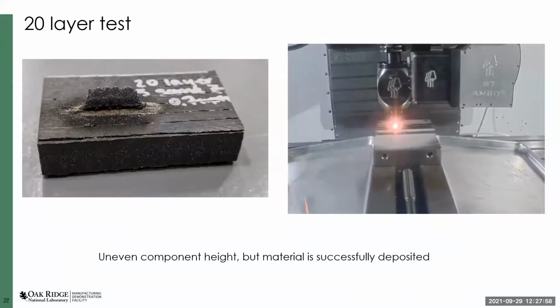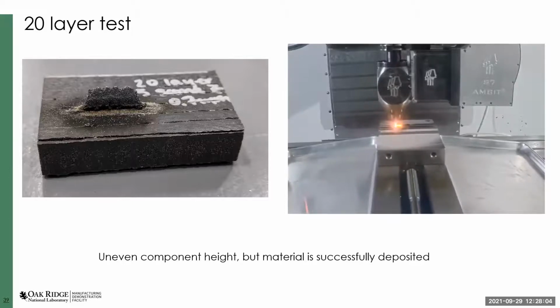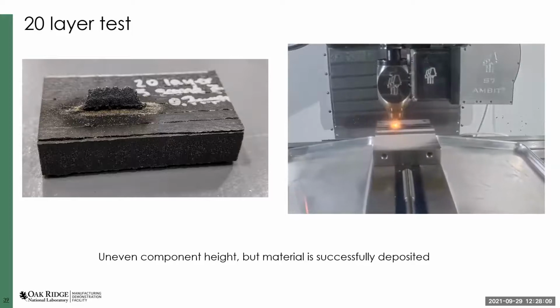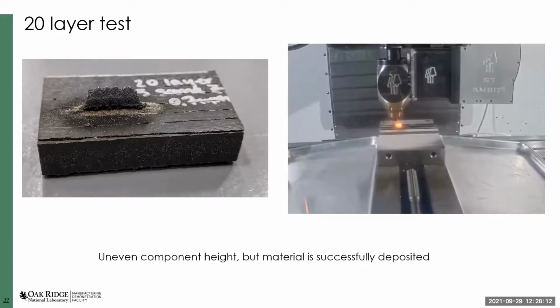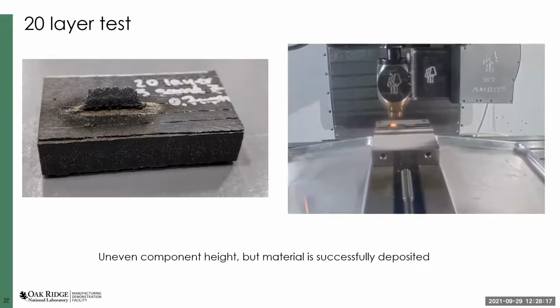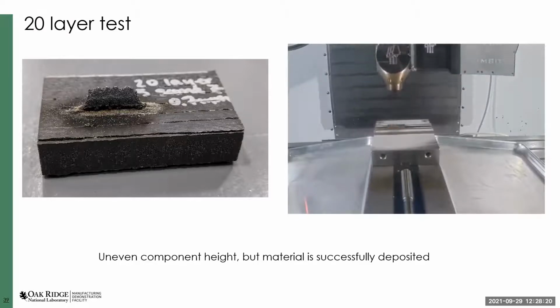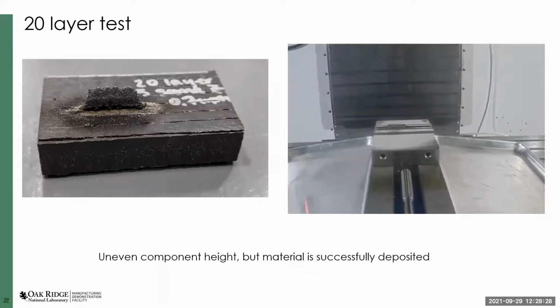You can see that initially there's still that pretty intense flaring, but that decreases over time as you stop hitting the polymer directly with the laser. You can see that the metal component remains hot, so it's pretty red hot in this image, but you can see that you are getting a buildup of material over time. And as you can see from this final image of the single bead wall that I built up, you don't see much degradation of the polymer with respect to melting. So this is still a pretty solid block of polymer that you have at the end of this experiment.